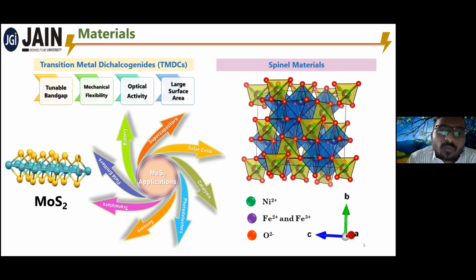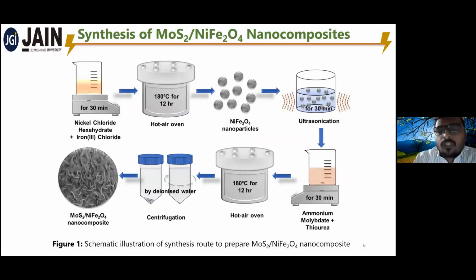We form composites of nickel ferrite and MoS2 by a simple hydrothermal approach. Initially, we synthesize the nickel ferrite nanoparticles using nickel chloride and iron chloride precursors with the help of the hydrothermal method at 180 degrees Celsius for 12 hours. Then we mix those formed NiFe2O4 nanoparticles with the precursors of ammonium molybdate and thiourea to form our desired MoS2 NiFe2O4 nanocomposites, and treat it in the same hydrothermal way, and we finally get our MoS2 NiFe2O4 nanocomposite.